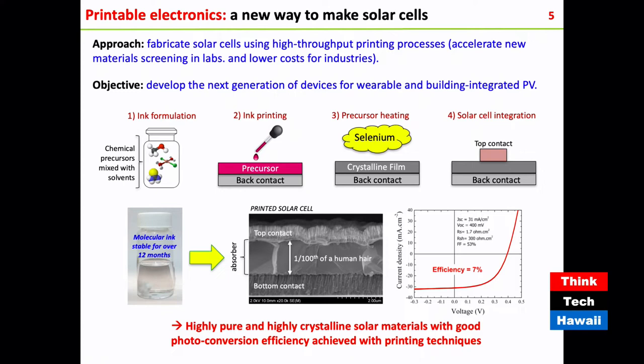That's fascinating. What you see on the bottom left is the ink that we form. It's very clear and very stable. We can store that ink for up to a year. The gray image on the bottom center is a cross-section of the solar cell. You take that picture using an electron microscope, which we have at UH, so we can do part of the analysis here at UH.